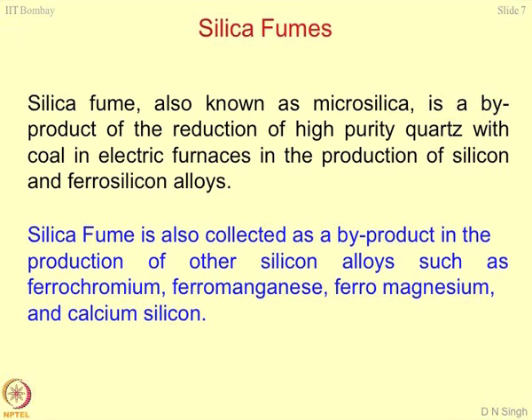Densification of silica fumes is a very big problem. If you can devise a technique to densify silica fumes, you can become a good industrialist. The specific gravity of these fumes is about 0.6 to 0.7, so an entire truckload of silica fumes will weigh only a few tons. Transportation of silica fumes is therefore a very big problem. Some people try to work on densification. Normally silica fumes are transported in liquid form — put in water so they at least achieve the density of water. However, this is not a very good method because silica fumes start reacting with water and lose their reactivity or pozzolonicity.